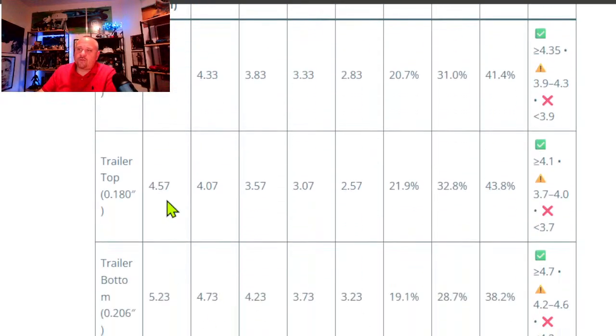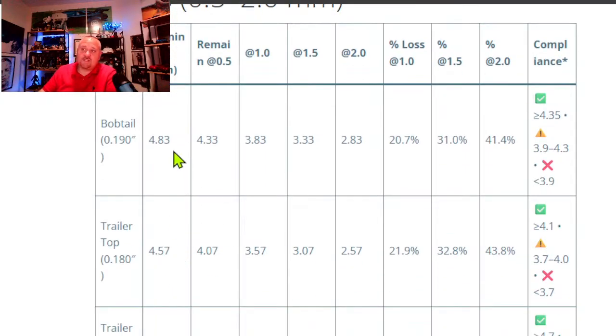Now, trailers, this is for tanker trailers, for the top. Same thing goes here. Nominal. Now, it's even less than a bobtail. They start off at a nominal thickness, which means ideal, of 4.57. Remaining at 0.5 millimeters worn off over time, washing, what have you, just normal wear and tear. The average for tanker trailers on the top half of the side, going up, is 4.07 millimeters. If you remove 1 millimeter, you're left with 3.57. With 1.5 millimeter removal, you're left with 3.07. With 2 millimeter removal, you're down to 2.57.